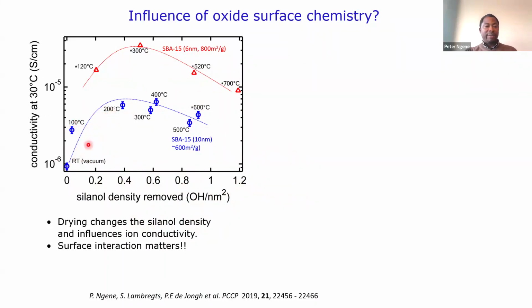What we do see is that if you don't dry the material, the conductivity is low, simply because you have a lot of water there, and this water is going to react with our lithium borohydride, the electrolyte, giving rise to something that is not conductive. So if you remove the physisorbed water and have only the surface OH groups, which is around 300 degrees centigrade, you see that your conductivity is maximum there.